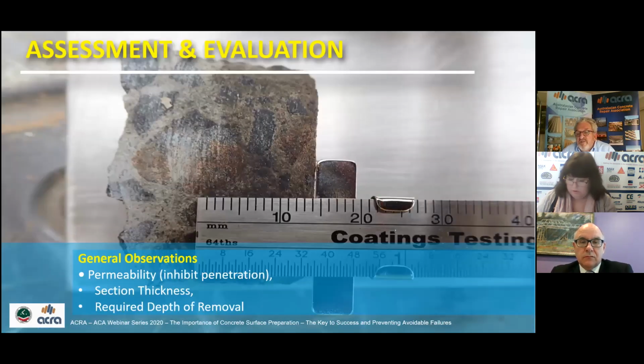The general observations, such as permeability, that may inhibit the likes of penetration, section thickness and required depth of removal. On that slide there, that's basically a bit of concrete that's been removed out of a transformer bund. You can see there that the oil has penetrated to probably about 14 millimetres in depth. So really, to get back to sound, firmly held parent concrete that's going to give a receptive finish, basically 14 mil has got to be taken off the surface of that to get something that we can actually bond to. Can't bond to the oil contamination, it's a release agent in itself.